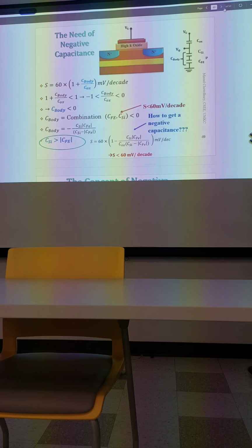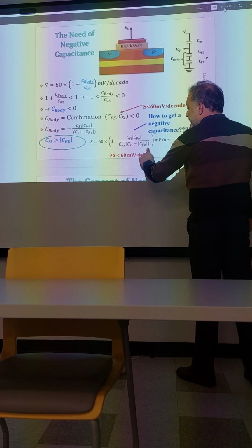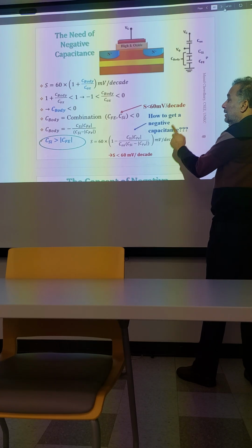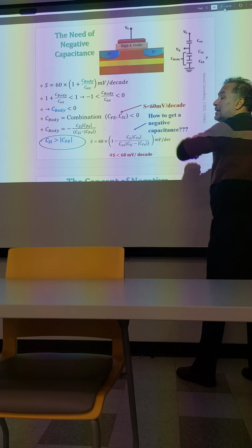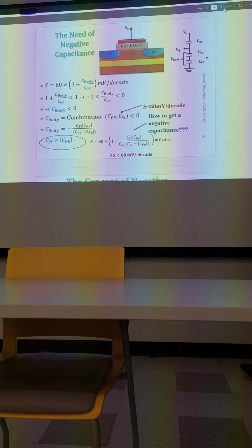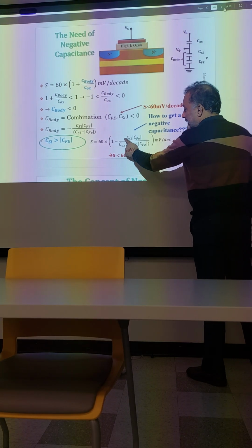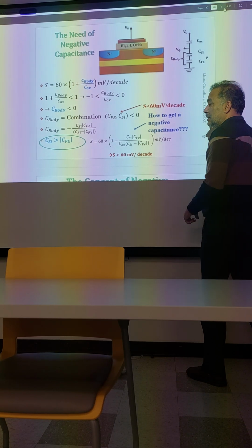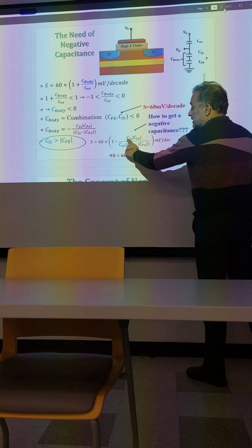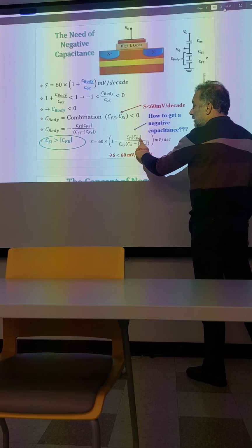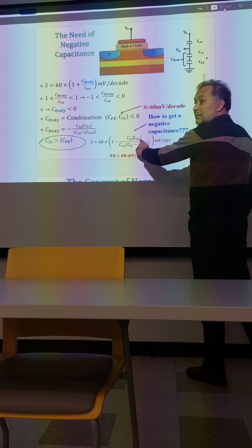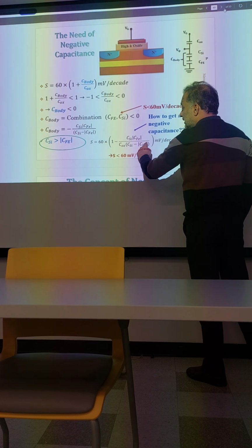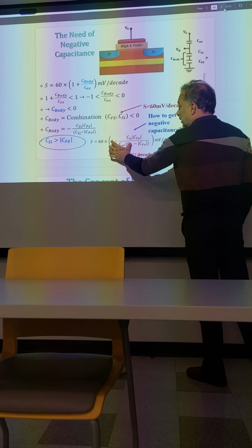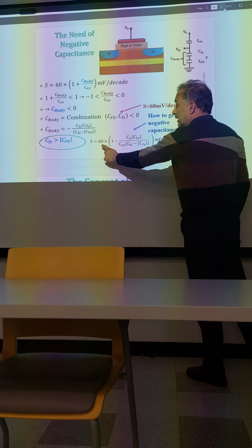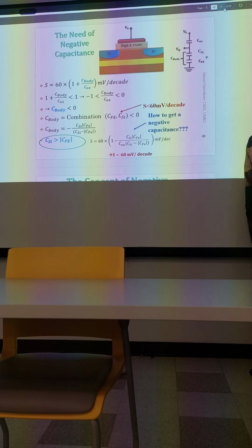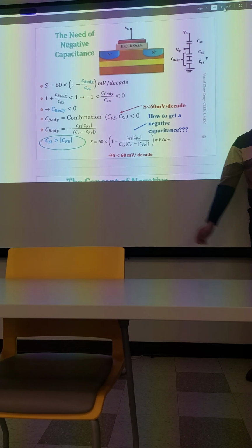So then we found the modified expression, and this has become our new modified expression with a ferroelectric insulator embedded inside the body of the transistor, and now we have 1 minus a fraction, which is lesser. Now by playing with the value of this capacitance ratio, oxide capacitance over ferroelectric capacitance, we can make this fraction larger and larger. Overall, this factor will be much smaller than 1, and the swing will go significantly below 60 millivolt per decade, so we have to play with this.